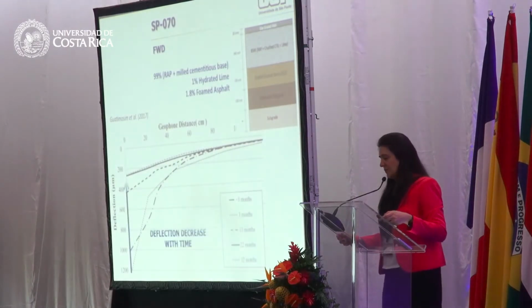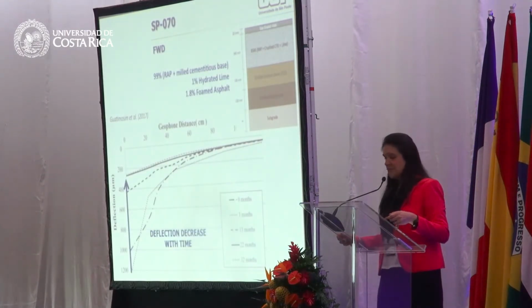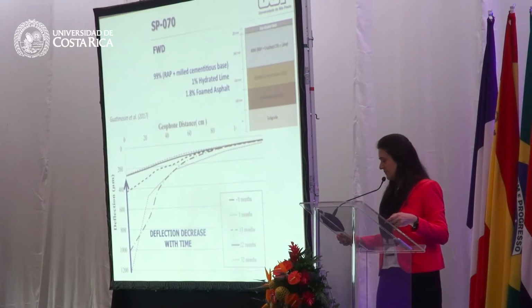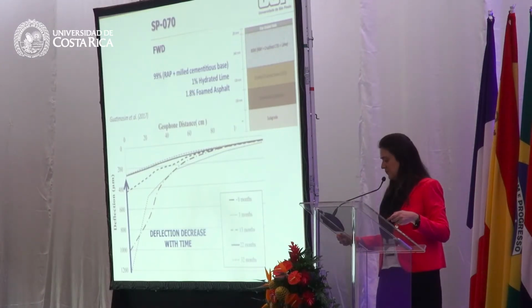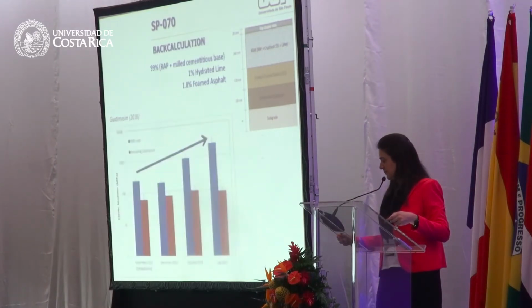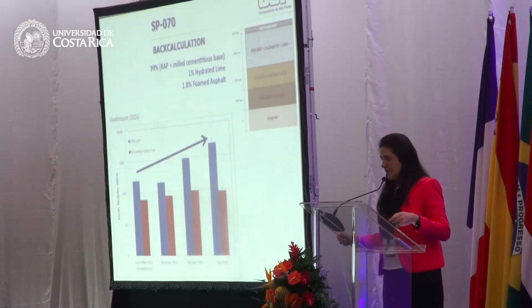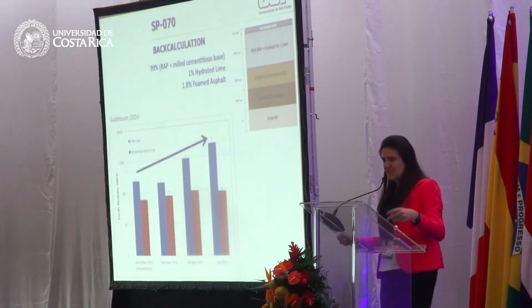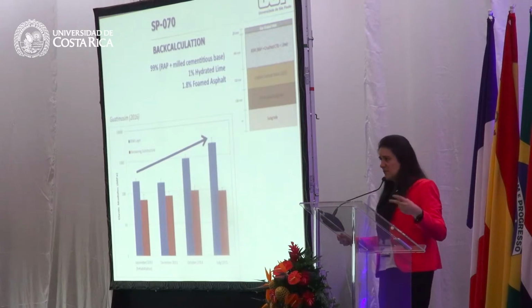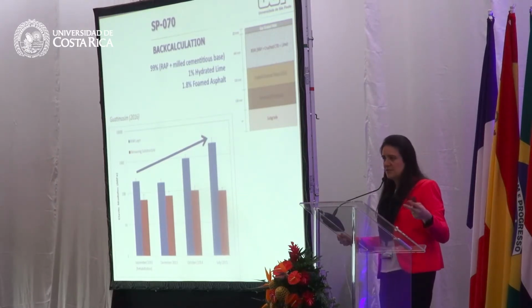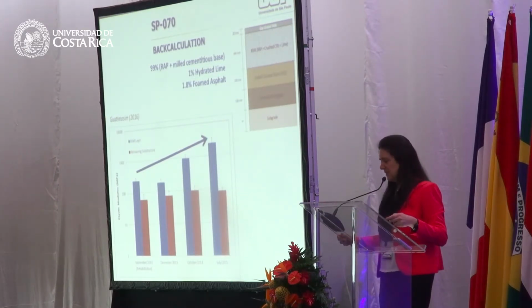And in there, we could also see a decrease in the deflection with time. At this one, after 3 years, almost 3 years. Some back calculation modulus, so if the deflection tends to decrease, the modulus of the materials tends to increase. We expected that.